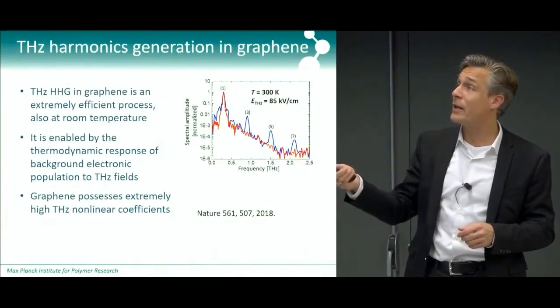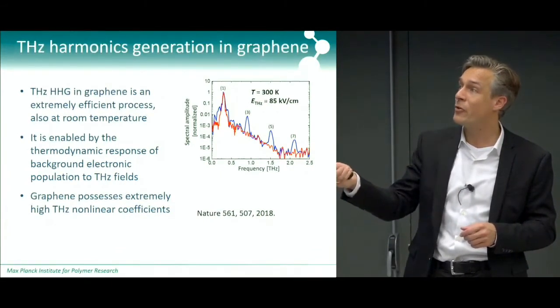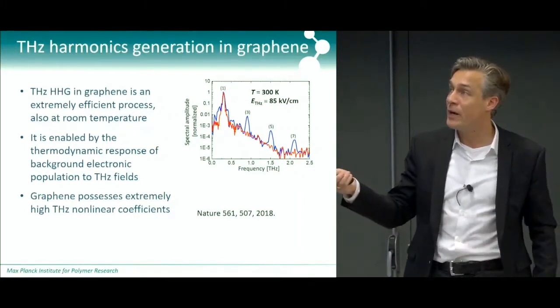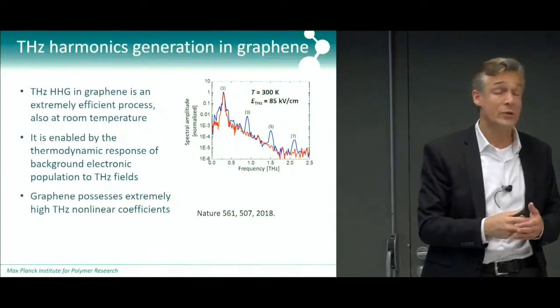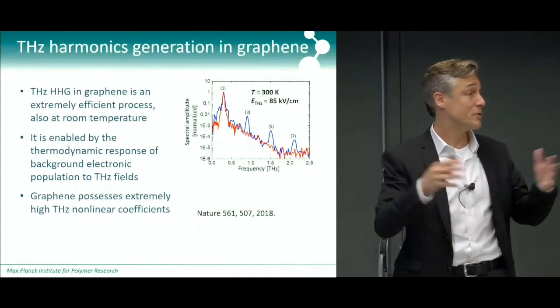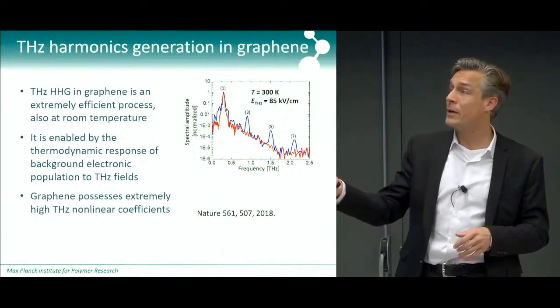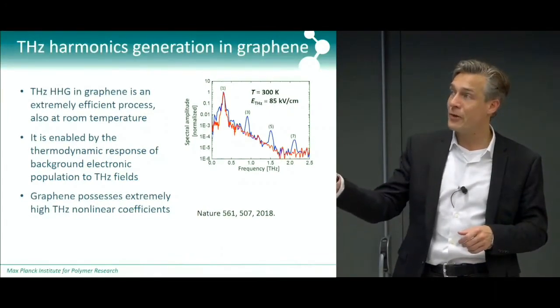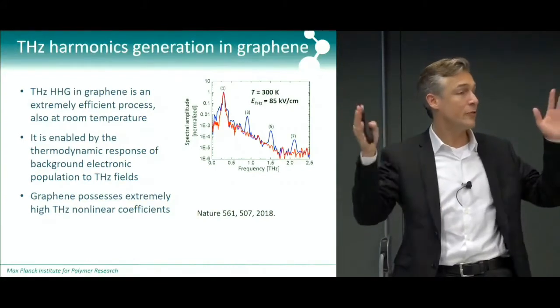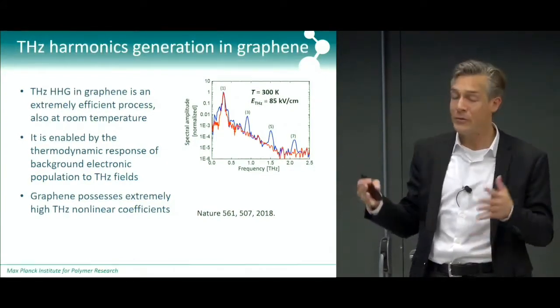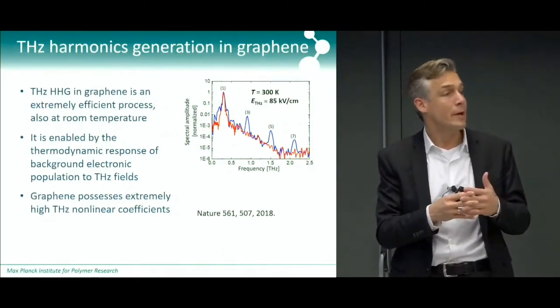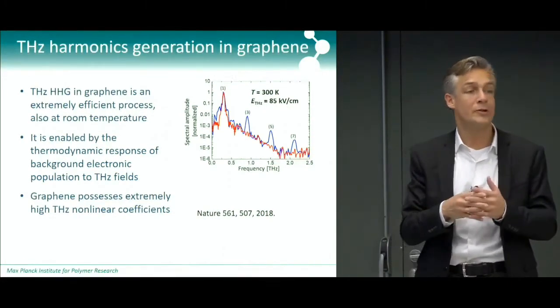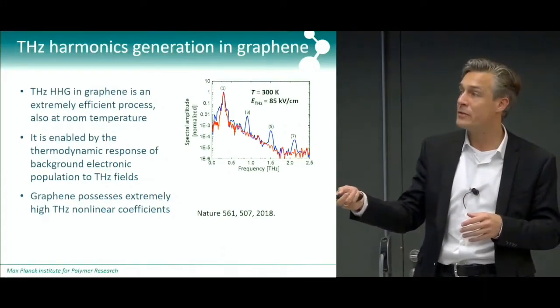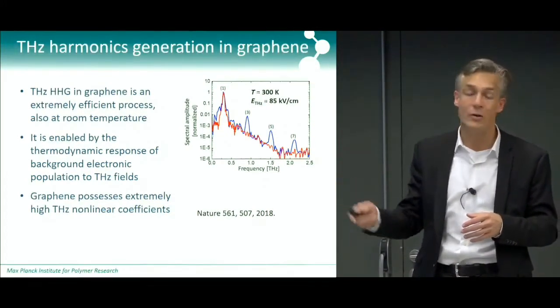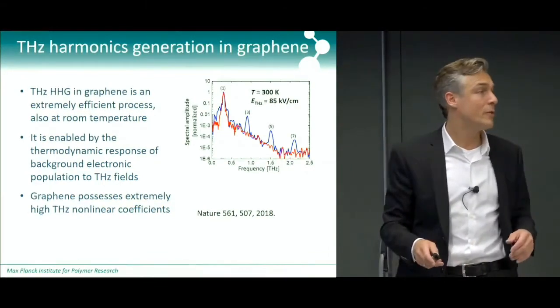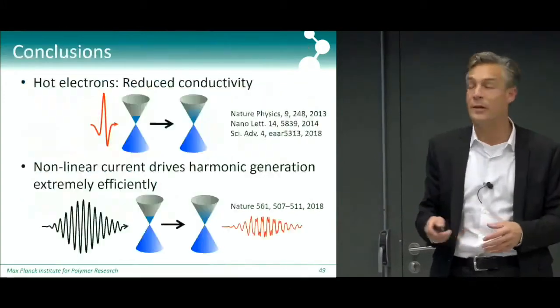So with that, I'd like to conclude, and I hope I've shown you that this high harmonic generation is very efficient. We did all these experiments at room temperature, so it just works extremely well. It's enabled by this collective heating and cooling of carriers, very simple physics underlying, but which is really fundamentally different from normal ways of harmonic generation in materials. And as a result, the effective nonlinear coefficients are many, many orders of magnitude higher than those in conventional nonlinear materials.